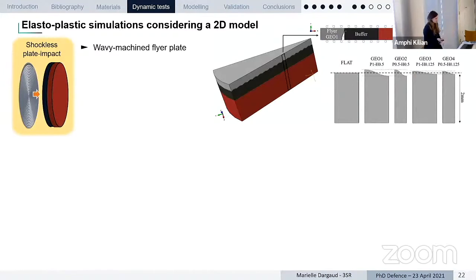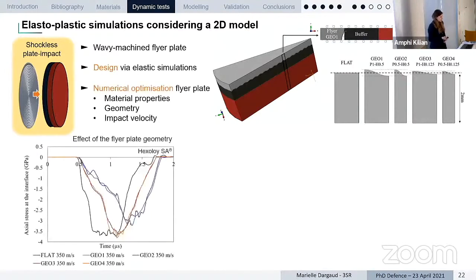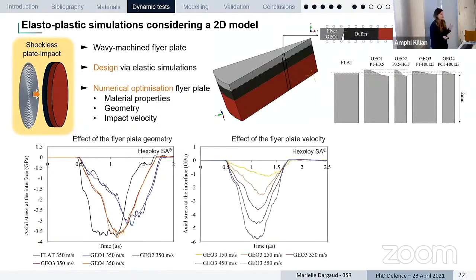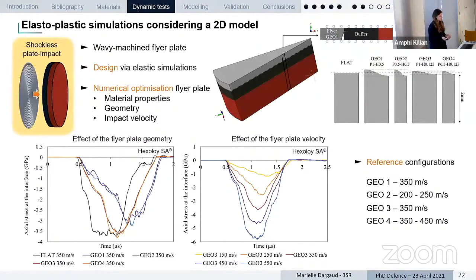We tried different geometries. Here you have 4 of them, playing on the height of the pattern. It is a cosine shape, and we are playing on the height and the period. We optimized numerically the shape of this flyer plate, playing on the material properties and on the shape of the profile. Here you have numerical results where we have a difference in the shape of this triangular pulse for different impactor geometries of the flyer plate. We also play on the impact velocity, which also has an impact on the shape of this triangular pulse. We selected the best configuration, where we could have a pretty good triangular pulse from the numerical simulations.